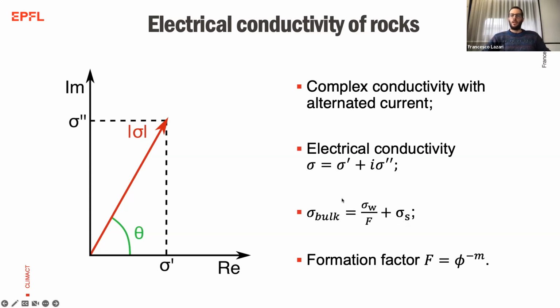So here we can see that the conductivity of a rock is determined by the conductivity of the fluid that is saturating it, which is proportional to the ion content of the fluid, and by the surface conductivity of the minerals, which we can roughly approximate to the content of clays of the rock. In particular, the formation factor, which is what we divide the water conductivity by, is given by the porosity of the rock raised to -m, which is the cementation factor. So we have a lot of information on the rock by only doing one measure of conductivity.